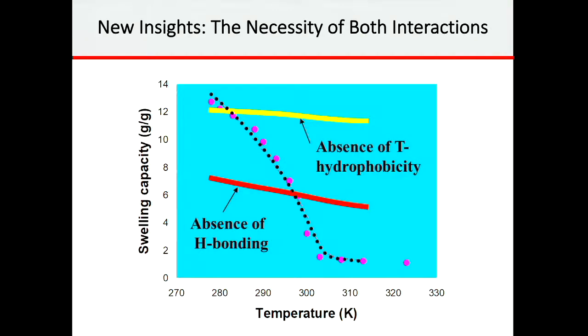The most important part I want to emphasize, however, is that when we started playing around with our model calculation, there were two things that became important. The first was, in the model, if we put in the absence of temperature-dependent hydrophobicity, you did not see any transition at all. If you knocked out the hydrogen bonding, you did not see any transition at all. But if you put in both of them, then you would get the transition. We were the first ones to actually bring out that both this hydrophilicity and hydrophobicity, and that is where the trapeze artistry started coming in. And as you can see, this is the trapeze artist. So what one is trying to say is that you have to balance out, and if you don't balance out, you lose out, so as to say.